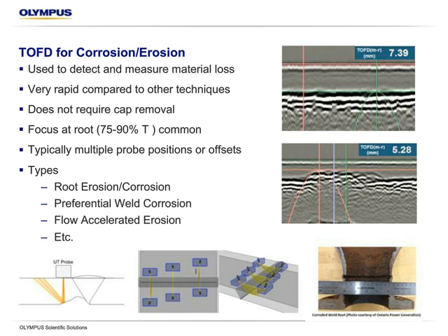Typically when we do this, to get proper measurement, very precise remaining wall type measurements, we're going to do a scan at maybe 3 different index positions. So it's kind of shown there in the bottom. This is going to increase our accuracy in the actual remaining wall thickness. So we'll do one centered around the weld, and then one offset one way, and then offset the other. This can be done all collectively if the unit can handle that many channels and you have the right scanner, or it can be done in 3 separate acquisitions and the data compared that way.